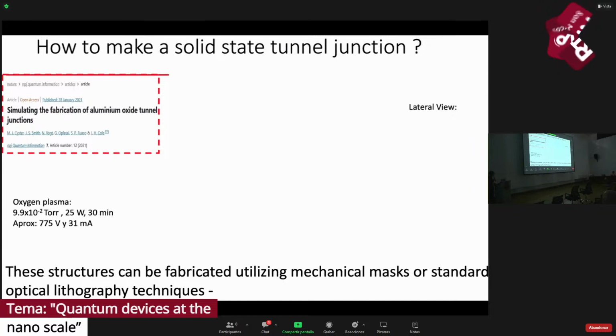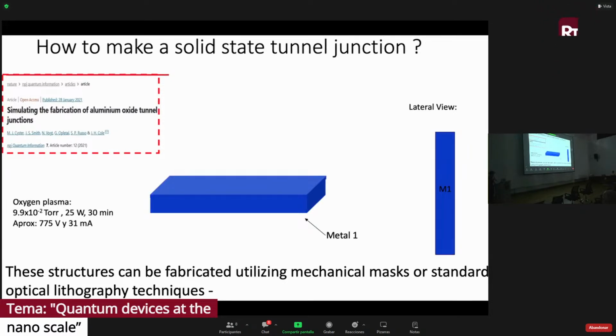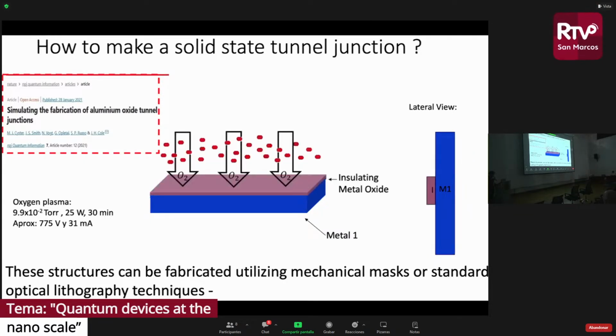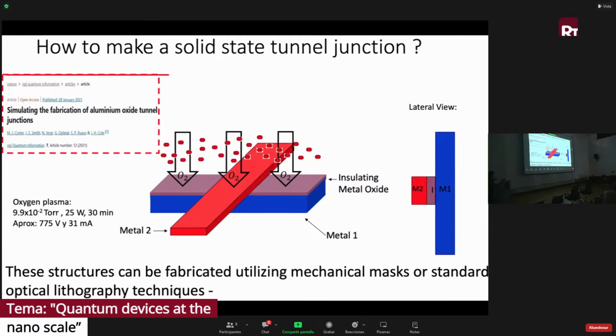So the basic idea is you have a metal layer, a metal contact, then you oxidize it with oxygen plasma, and you get a very thin layer of oxide that is around 2 nanometers, very uniform, and then you have the metal on top. And that would be the basic tunnel junction. There are others that you can do, but this one is the basic architecture, and you also have to put silicon oxide on top. And there are some properties like the barrier height.